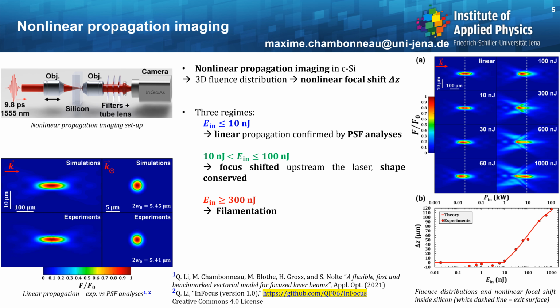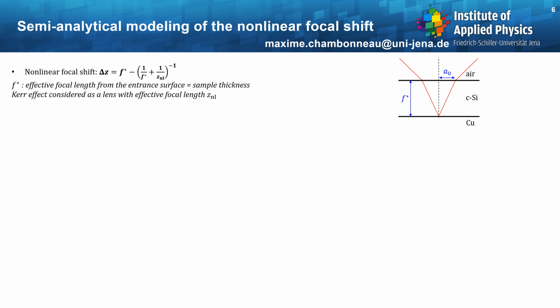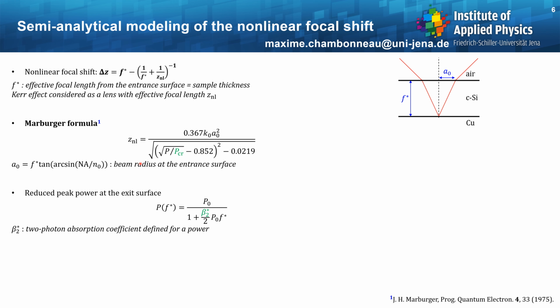In order to theoretically predict the behavior for the nonlinear focal shift as a function of the input pulse energy, we have developed a semi-analytical model relying on this equation shown here, where delta z is the nonlinear focal shift, f star is the effective focal length from the entrance surface of the silicon sample, which is nothing else than the sample thickness, and z NL represents the effective focal length associated with the Kerr effect, which is considered as a lens.